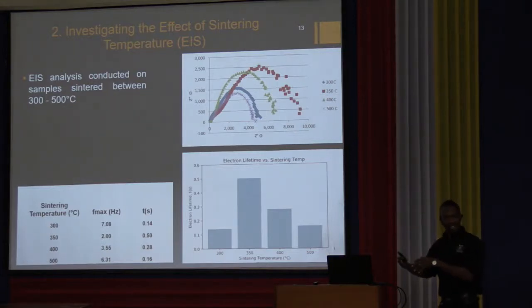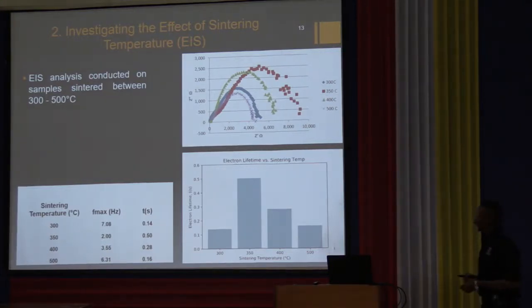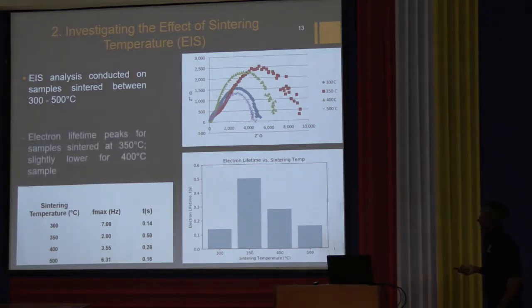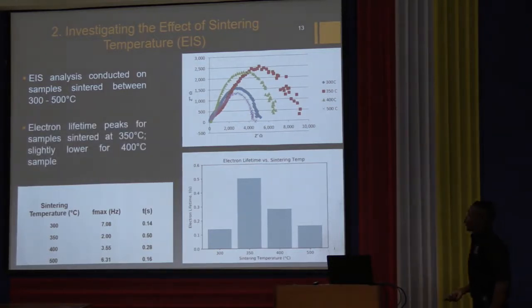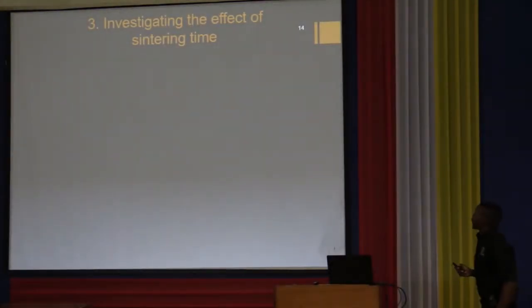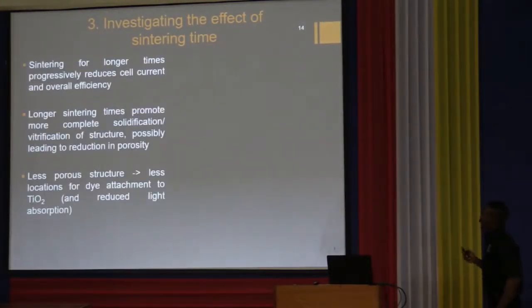Again, slightly less than the best performing temperature we saw earlier, but still in the range. And this is telling us again that 350 degrees to 400 degrees is an ideal range for preparing our samples. All right? Now, the final thing we did was to investigate the effect of sintering time.